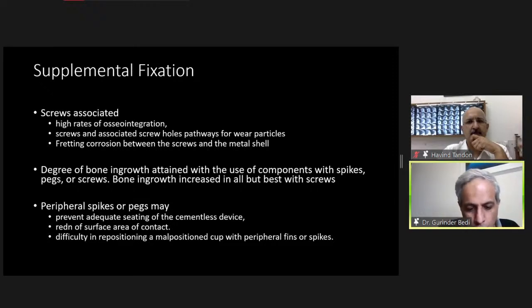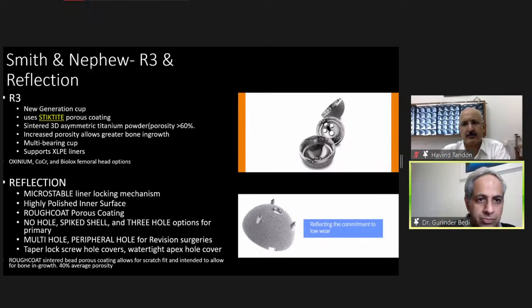Although there are problems because the screw holes can actually allow the migration of wear particles and cause osteolysis, the amount of osseointegration is actually better. What about using spikes, pegs and all? The answer is they do definitely allow you better osseointegration around the screw, except that sometimes they don't allow you to seat it properly, and sometimes they can actually reduce the surface of contact where it doesn't go in, and then if you have to change it, it sometimes causes a problem.